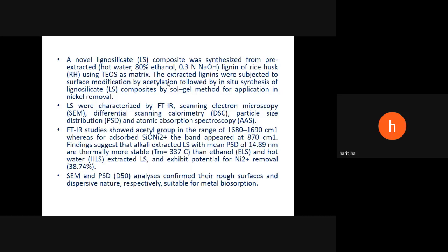So the findings suggest that the alkali extracted lignin silicate with mean size of 14.89 nanometer is thermally more stable than ethanol lignosilicate and hot water lignosilicate. So they have higher potential for nickel removal also. SEM and PSD analysis also confirm that they have a rough surface and dispersive nature, respectively, suitable for metal biosorption.